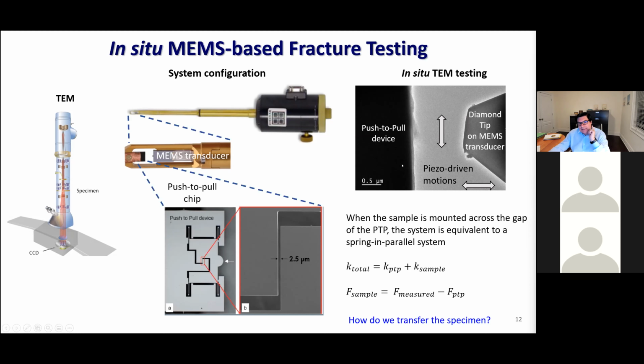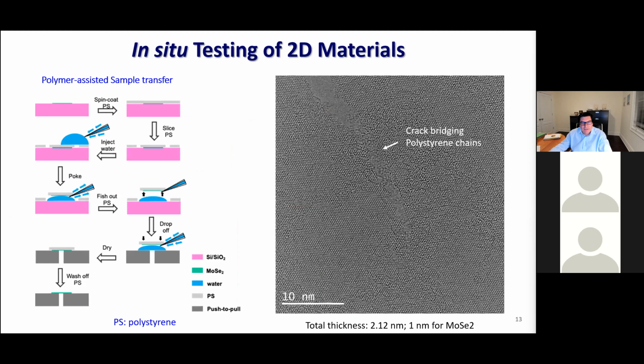So this is nice and it works very well, but the challenge here is how you transfer a flake of this 2D material onto this device. And there is where the complication comes and what makes this type of experiments quite challenging. The success rate of doing that successfully is very low, and we develop a technique that many people use in